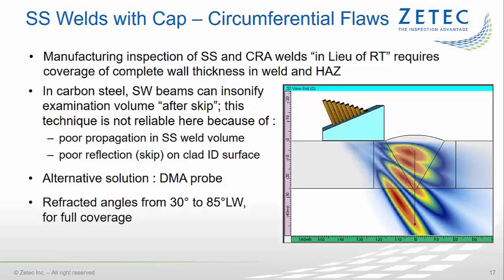Let's start with a frequently encountered configuration: homogeneous stainless steel plate and pipe welds with the weld cap in place. Manufacturing inspections of stainless steel and corrosion-resistant alloy or CRA welds in lieu of RT require coverage of the complete wall thickness of the weld volume and the heat-affected zone.